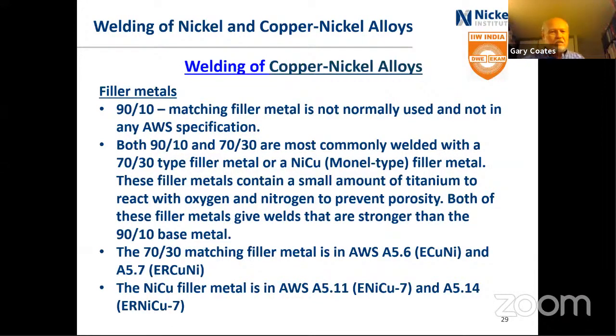However, titanium in the filler metal, especially with the stick electrode, makes welding more difficult or ugly, or whatever we want to call it. So there was a question right at the beginning about titanium in these materials, that sometimes there isn't enough and you're getting porosity. It's a bit of a problem. You don't want too much in there because you get really ugly welds, but you don't want too little or you get porosity.